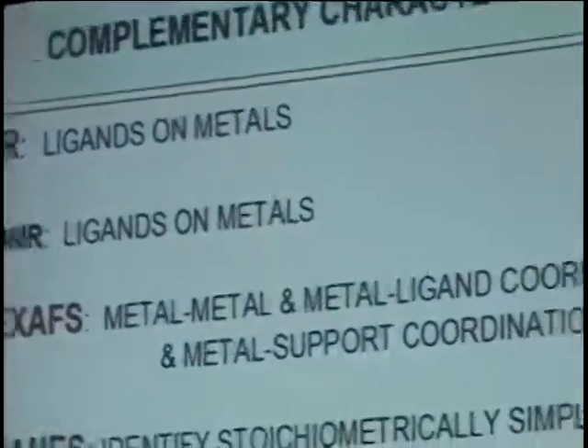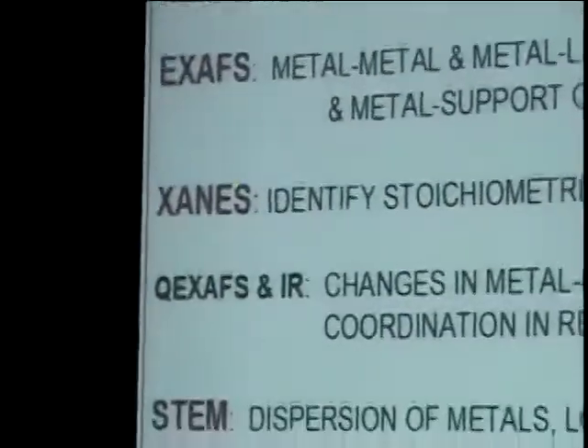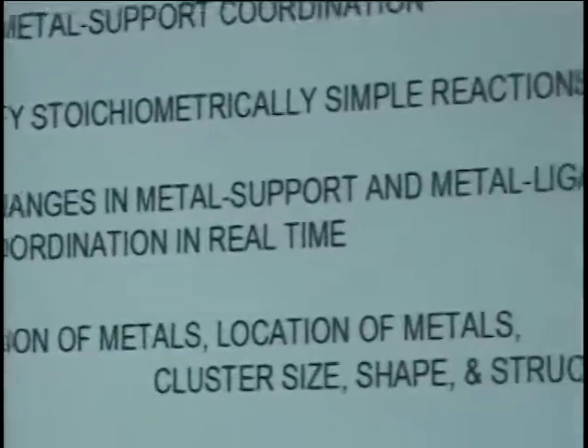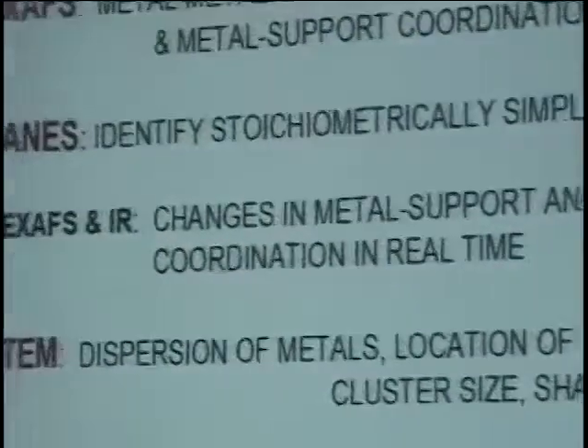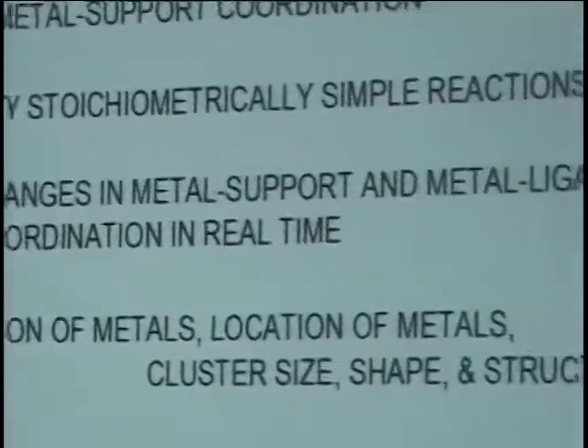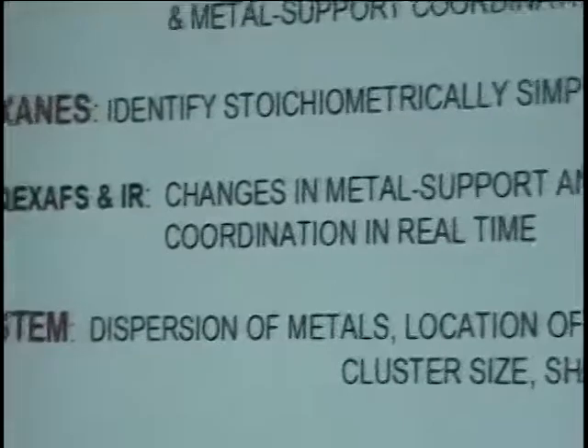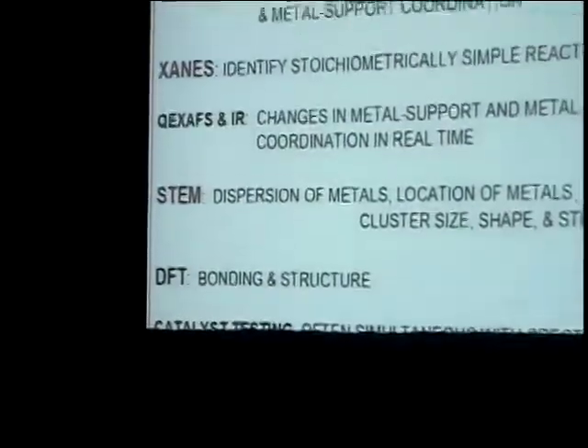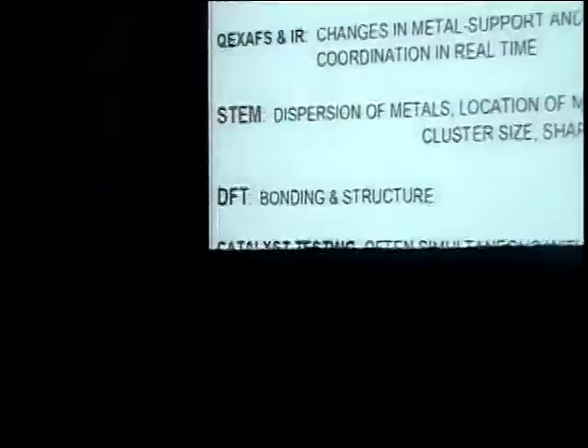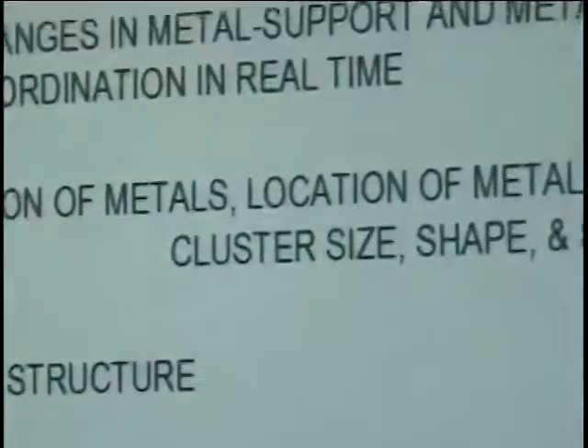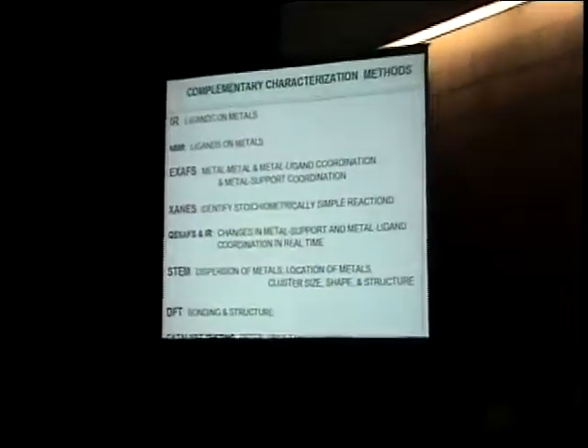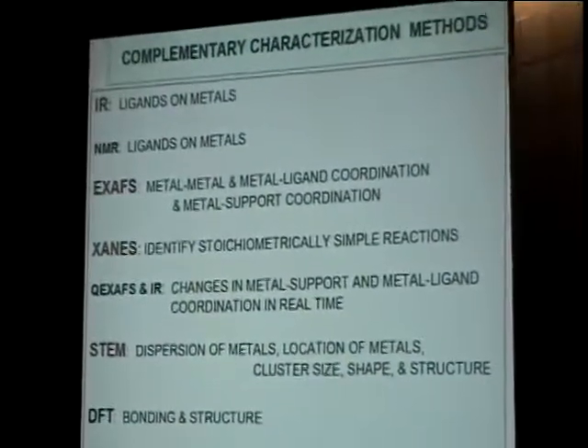The carbonyls give a lot of information in the infrared spectrum. XAFS is crucial for all of this to get structural information that complements the microscopy, or probably I should say vice versa. And XANES, turns out, we're learning that XANES is especially important to track conversions of one species to another. And when there are isosbestic points, then we see we have a stoichiometrically simple conversion. Sometimes we do. And when we don't have those isosbestic points, then it's more complex stoichiometrically, which is typical. So we get a lot of information relatively straightforwardly just by looking at the XANES, even if it doesn't provide too much structural insight.